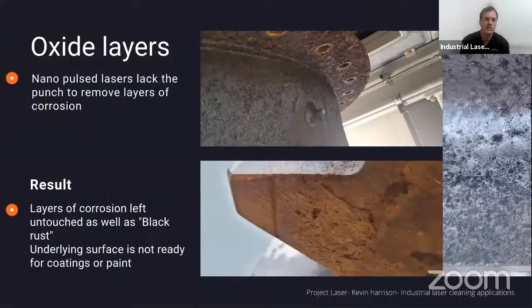Yeah, so this is going to be a couple of issues with laser cleaning. When you shop for a machine or research machines, they often say they're there to remove oxides and paint, and those are two of the things that I basically leave until last. Nanopulse lasers, specifically top hat lasers, don't have the punch to remove thick layers of corrosion. As you can see with these two examples, those thick layers of corrosion I could just flick off with my fingers. If you pass the laser over that, it doesn't have the abrasive power to remove it.